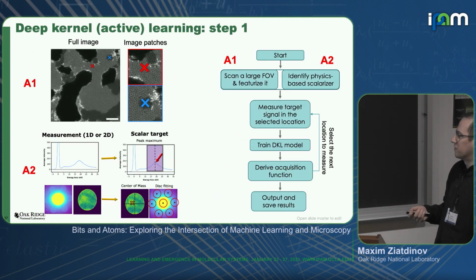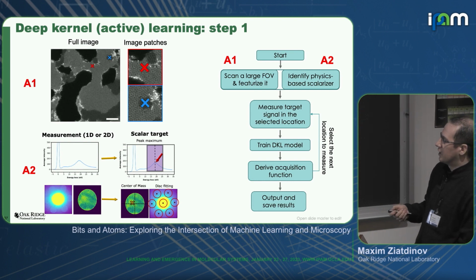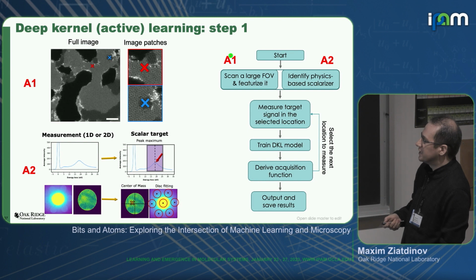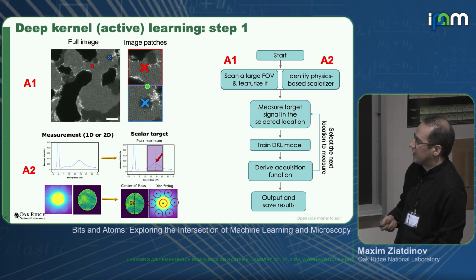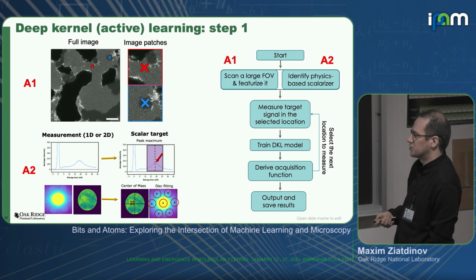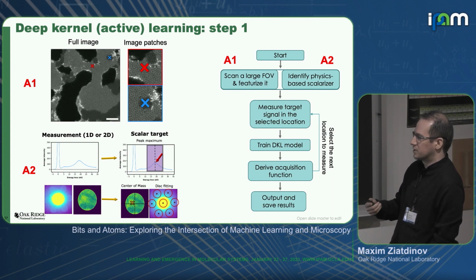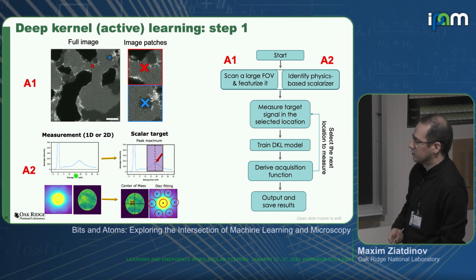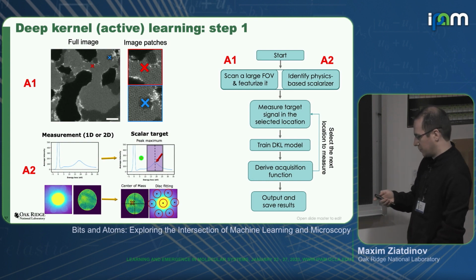Of course, you're probably all familiar with the active learning and Bayesian optimization setup, so it looks very similar. It's pretty much what it is. There are a few changes that we make at the initial stage of this workflow. Basically, we start with obtaining a large image over a relatively large field of view. We split it into image patches at each pixel, right? And then the second thing that we do is that we create what we call a scalarizer, which is basically how we convert our spectroscopic data into a physical property of interest, right? It could be 1D spectroscopic data or 2D spectroscopic data, but the idea is that there is a particular behavior that we're interested in, so how do we convert that measured spectra into that behavior? And there are almost infinite possibilities for how we do it.